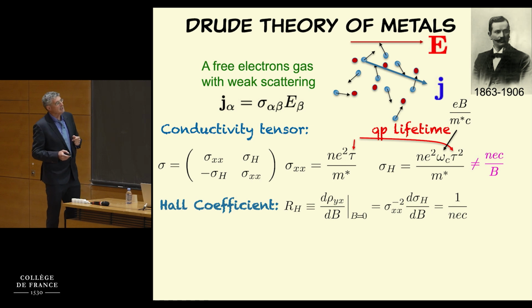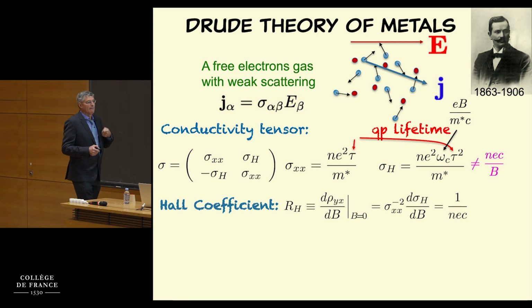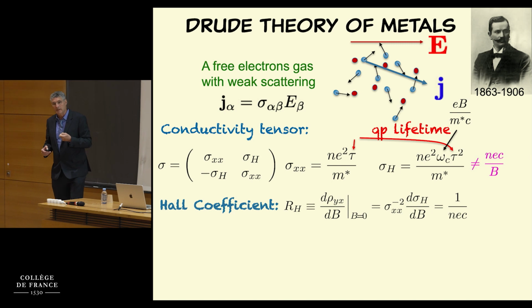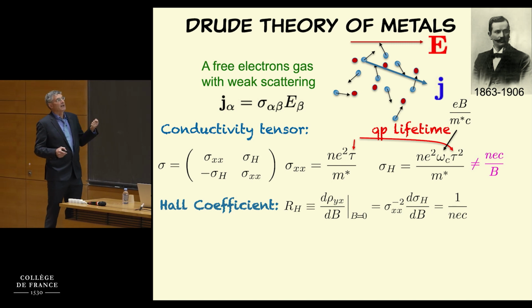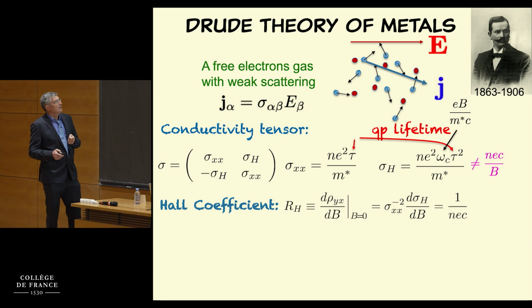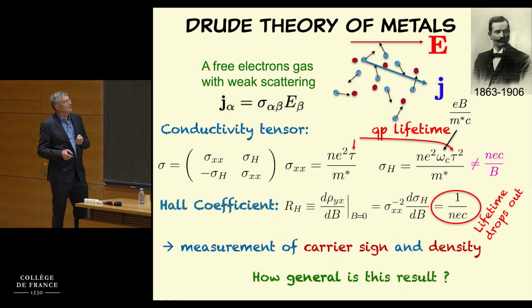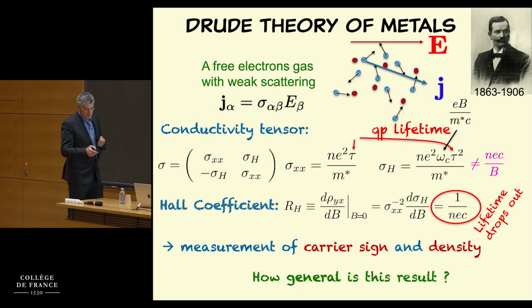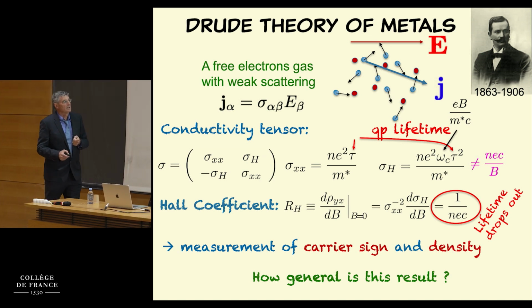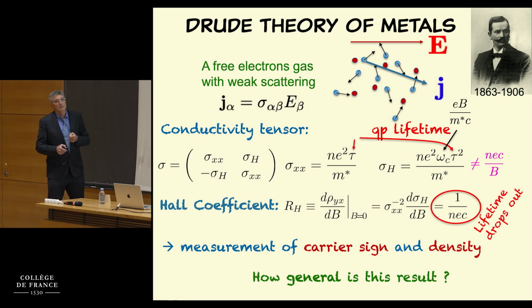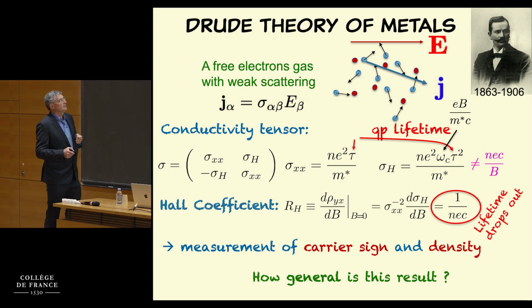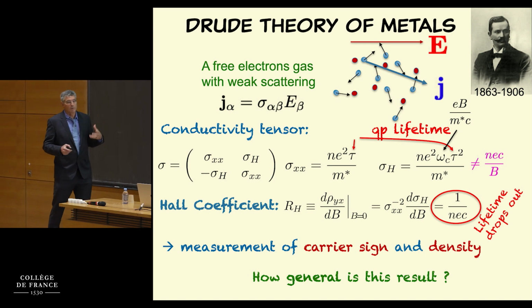And the funny thing about this relation is that it relates a quantity that you measure by essentially transport. And transport is a dynamical response function. It's something that has to do with time dependence. You would expect it to depend on lifetimes and all that, but it doesn't. So is that a general property of the Hall resistivity? The statement that I want to make is that, in fact, it is. But it's not this simple relation in general. Rather, the fact that this coefficient is a thermodynamic coefficient, one determined by statics, by equilibrium quantities of the metal, is actually general.